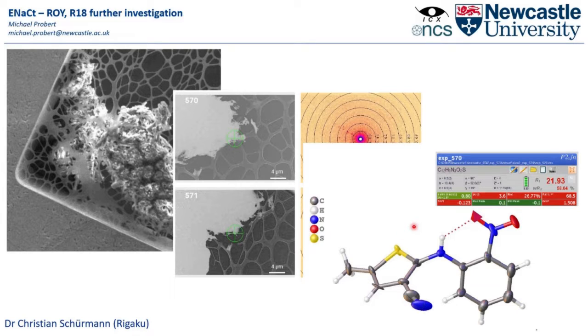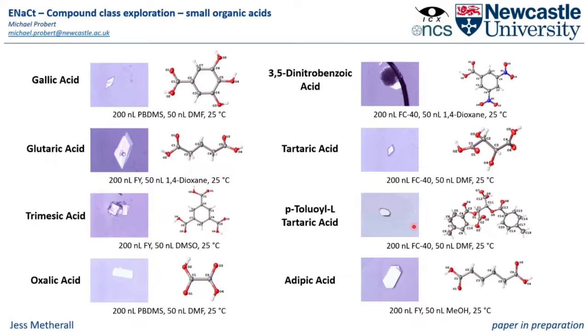So we've seen then that we can generally use this technique for crystallization of compounds, and we've seen that we can use it for analysis of polymorphism. What about if we wanted to do systematic studies, though? Because we now have a highly parallel crystallization approach, we can start analyzing compounds to look for trends across the systems. So again, for an easy starter, we started with a class of compounds that we were likely to get crystallization from, but we looked at the small organic acids, and crystallization of all of these compounds is easily achieved with large high quality crystals grown, all of which are suitable for analysis and all of which give good results.